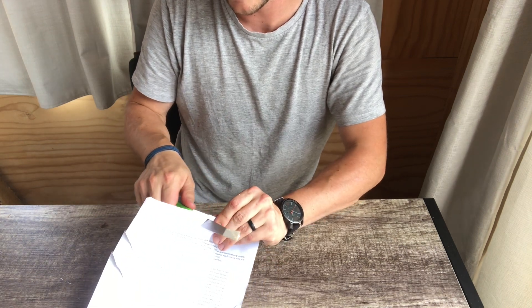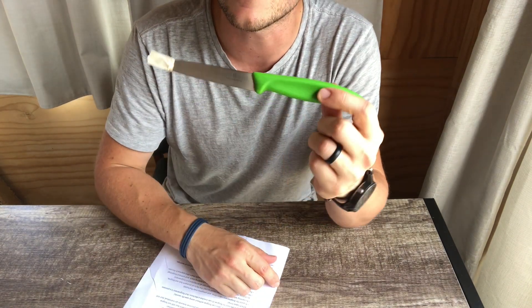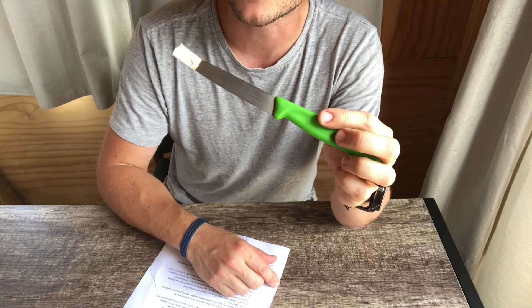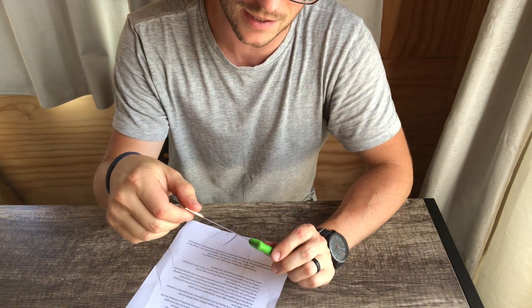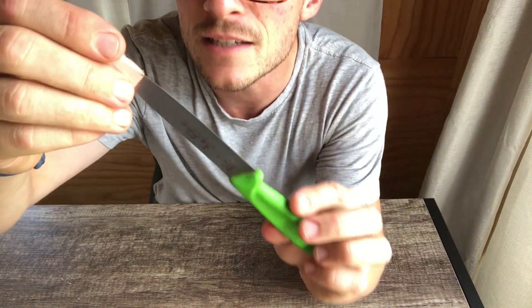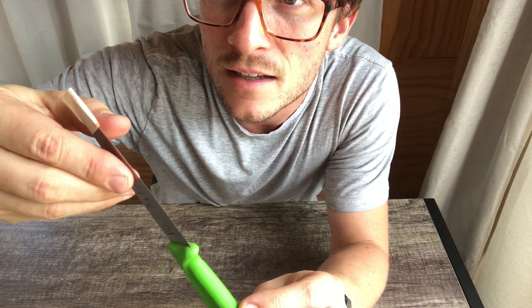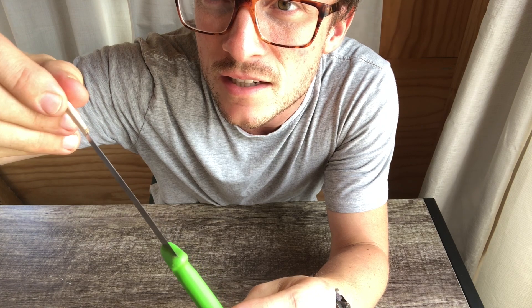I think that's a bit of a red flag that this actually might have left a bit of a wire edge, where the Spyderco Ultra Fine didn't. And the wire edge cut through the rope decently well, but once we smacked it into the pine block, it may have just destabilized and bent over. I can visibly see some — I don't know if I can catch it on camera — there it is. Do you see that? It's flattening evident. You can see there's like a little white reflection in the sun. That's not really been the case for a lot of the others.